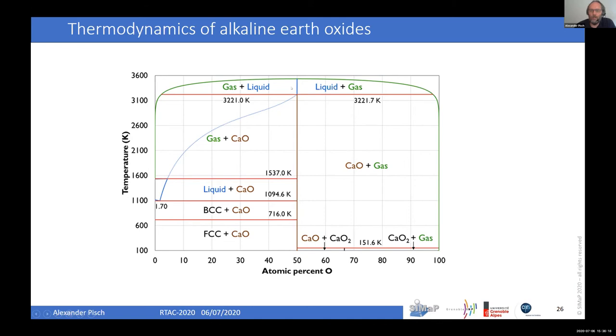And in pure CaO, the congruent melting point is 3,222. And here the assessed one in one bar of oxygen is 3,221.7. And when you go to lower oxygen partial pressures, you get a lower value. So therefore, always be careful when you trust the melting points of very high melting materials, as the oxygen partial pressure may be a tricky parameter to control experimentally, and therefore the values should be taken with care.